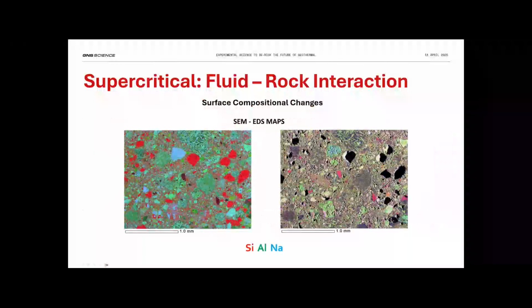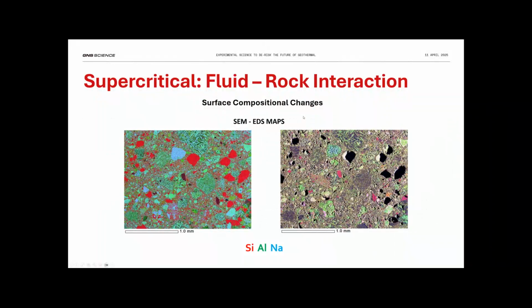This also shows an EDS map of the surface of the rock. And you can see that on the left is the unreacted rock. The red is silica, the green is alumina, and the blue is sodium. And you can see the reacted rock scanning the exact same region. These black holes are shadows. Actually, the silica is gone. And there's quite a bit of sodium also removed from the surface too. So we can see that this supercritical fluid, this is distilled water, by the way, is actually removing quite a bit of material from the surface.